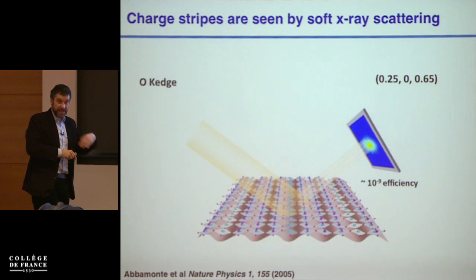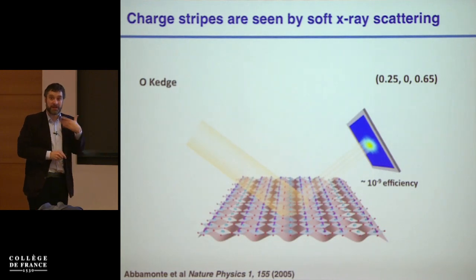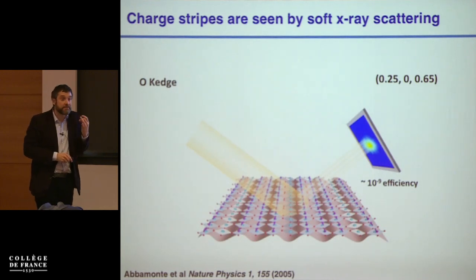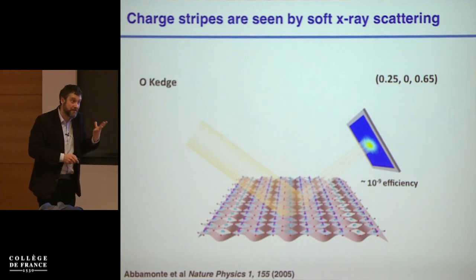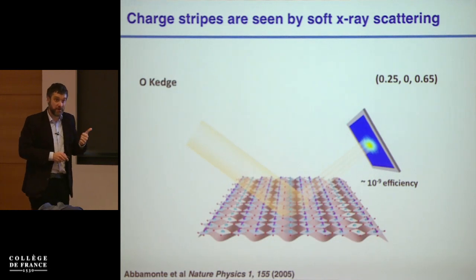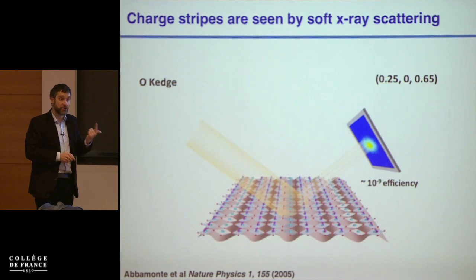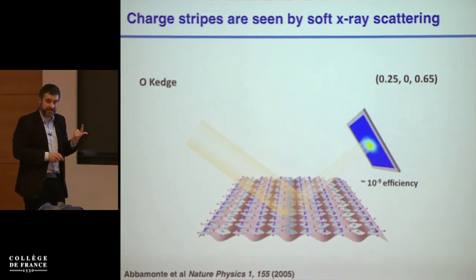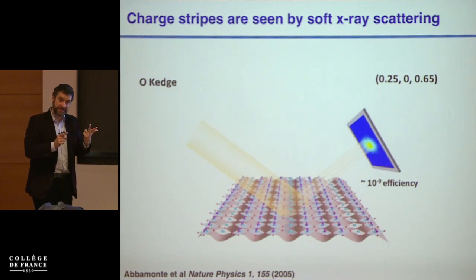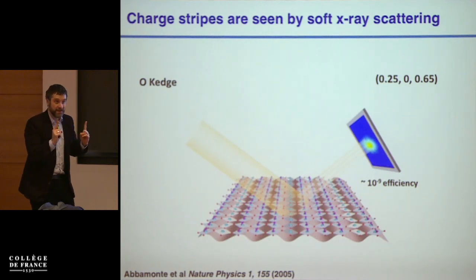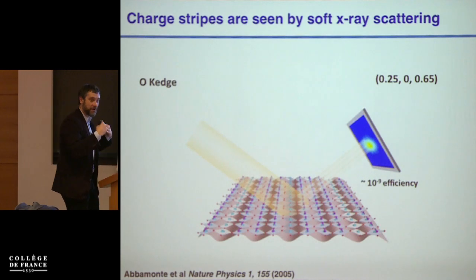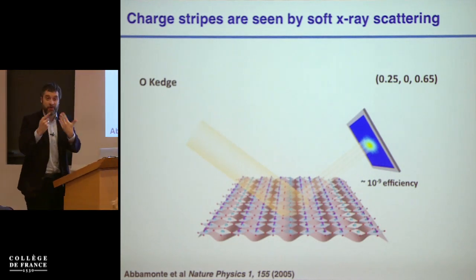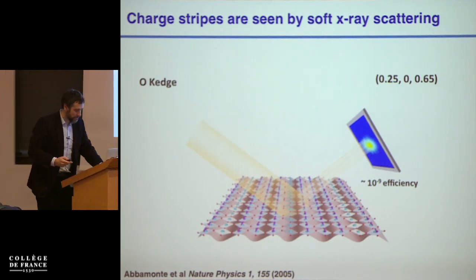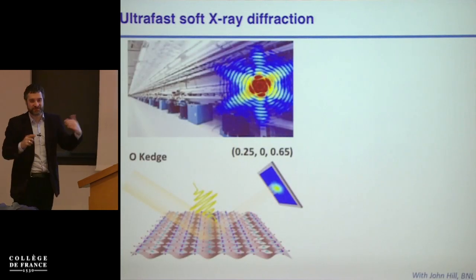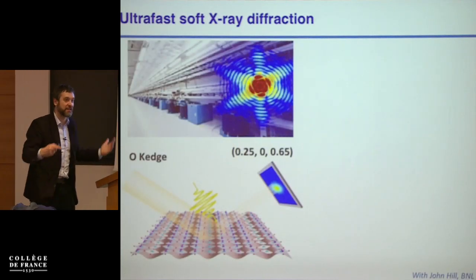So only by going resonant at the edge, I can have a diffraction peak that is only 10 to the minus 9 efficient. And this is the reason why, if I want to do femtosecond X-rays, I need something very special. I need a source that has a lot of photons, that is tunable to the copper oxygen edge in this case, and makes short pulses that can be synchronized to the vibrational pump and then moved in time. So this is actually quite amazing, that free electron lasers allow us to do this. We write the proposal, it gets rejected, then we write it again, etc.